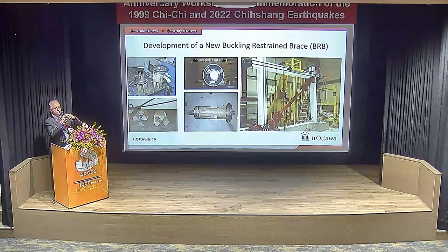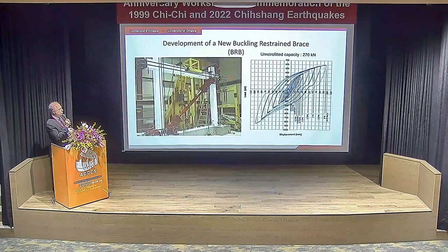So we created these fingers that would move in and out. They would engage, and throughout these tension compression cycles, the inner circular bar that we use would continue to be supported. So that gave us a fairly good response. On the right-hand side, you see hysteretic response of this frame, and as compared to 270 kilonewton capacity for the unbraced frame, there was a 3 times improvement in strength, and the non-ductile frame was able to go up to